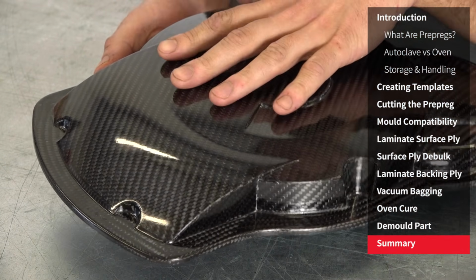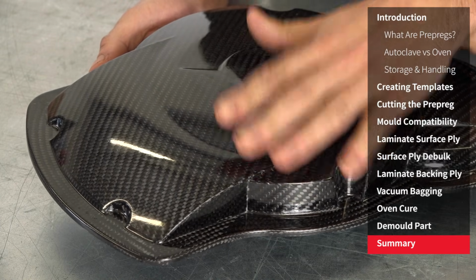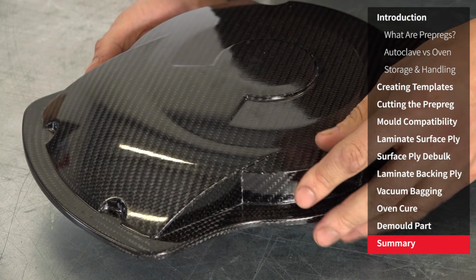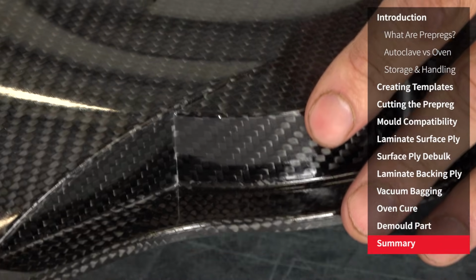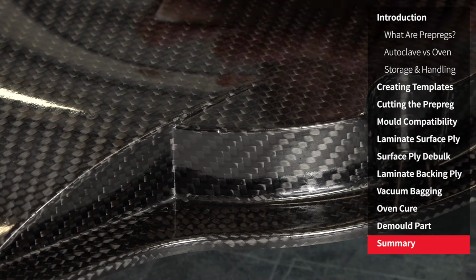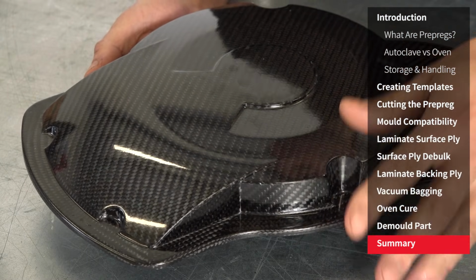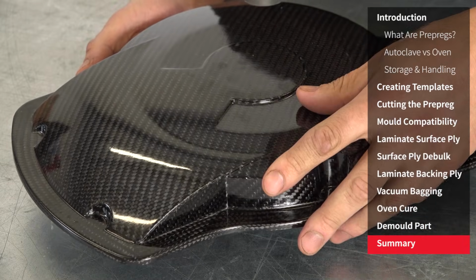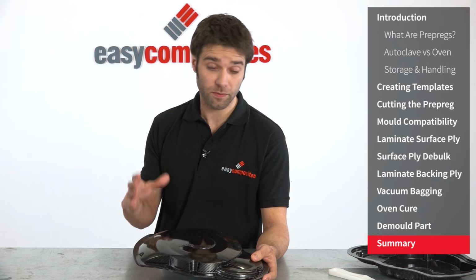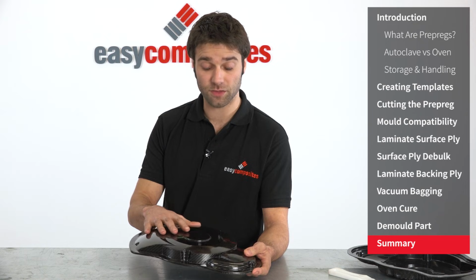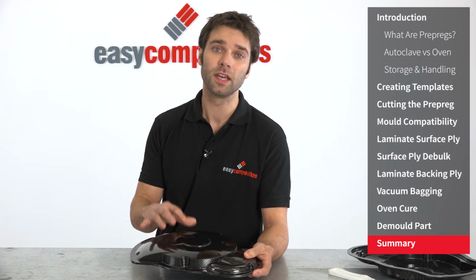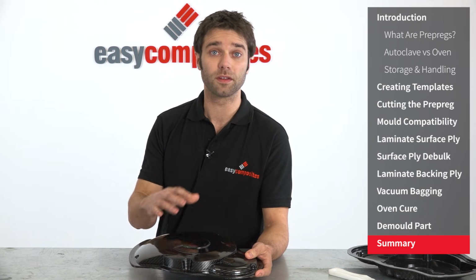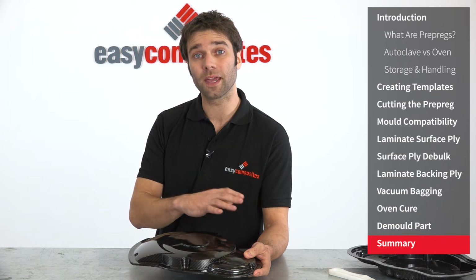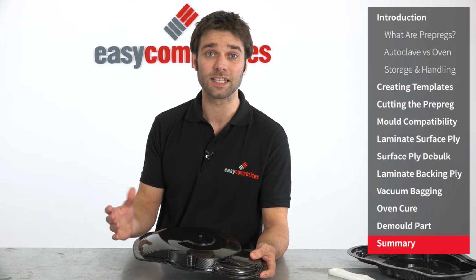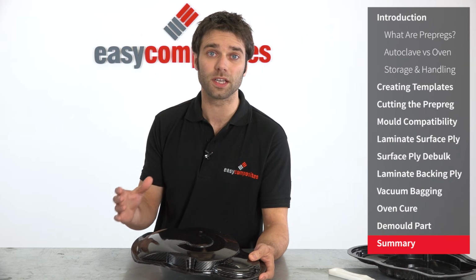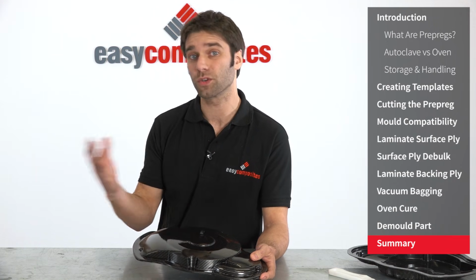So it's clear to see the excellent results that can be achieved using the XPREG XC110 system. We have a pinhole-free finish across the surface of the part, and there's no evidence of voiding or imperfections on these difficult 90-degree corners, which was no doubt helped by cutting and joining of the material in these areas, careful laminating and proper vacuum bagging technique. Although in this tutorial we've used the XC110 system to produce this relatively small engine cover component, the excellent mechanical properties of the prepreg system allow it to be used to make fully structural components of any size. In fact, we have manufacturers using it to produce everything from bike frames through to airframes.